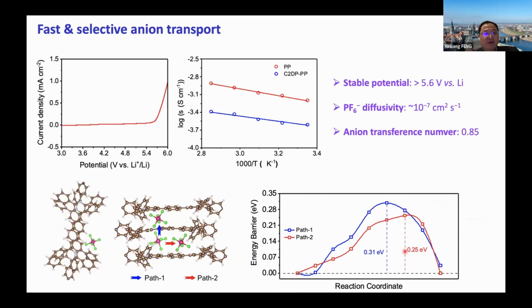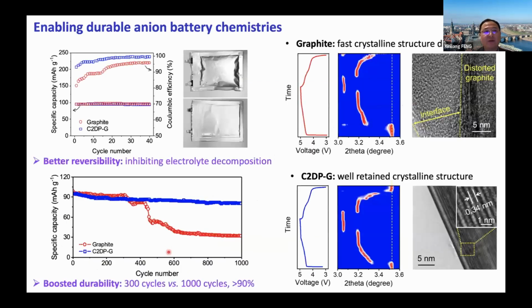So we first evaluate the voltage window. They basically are stable against lithium up to 5.6 volts, which is a pretty broad electrochemical window, very stable. They have very good diffusivity towards selective anions, with a very good anion transfer number. And from theory, we can model the transport mechanism. Basically, anions can go through the wider pore channel, and they can also go through wider interlayers. So both channels can be favorable, with decreased energy barriers through the 1D pore channels, which suggests that a very ultra-thin film is very good for that.